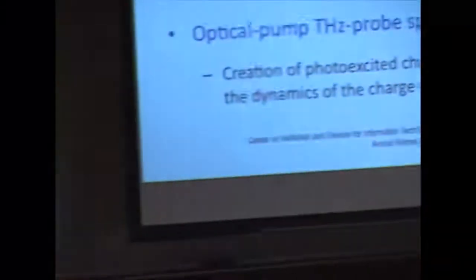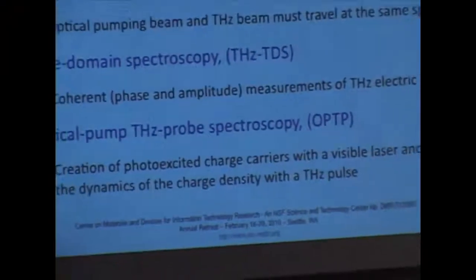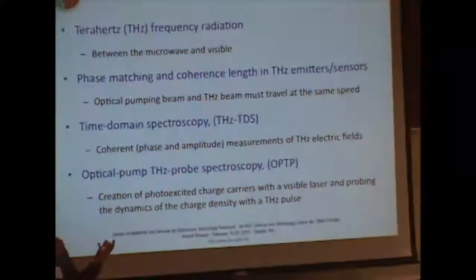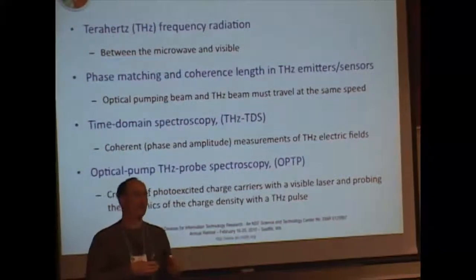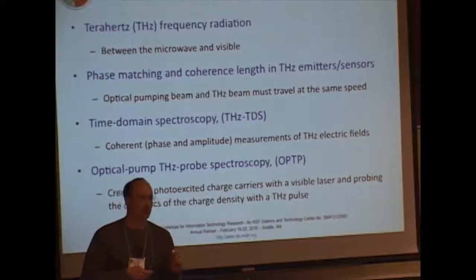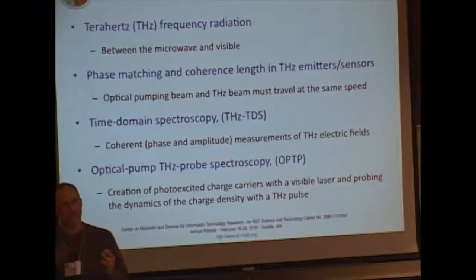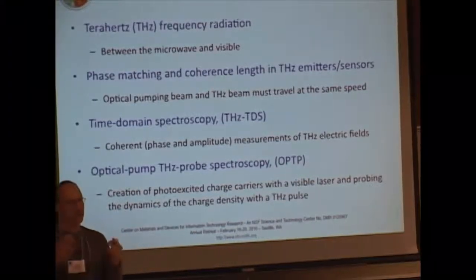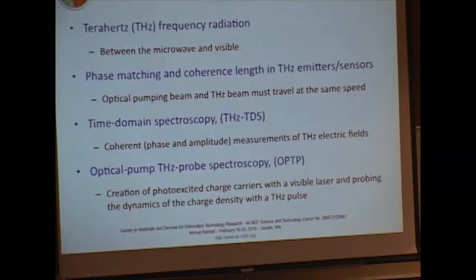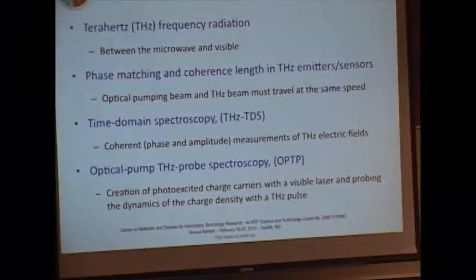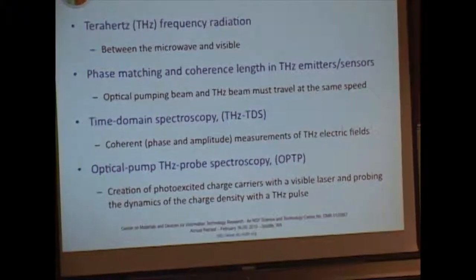And the last sort of vocabulary is optical pump terahertz probe spectroscopy. And this is what we're doing with organic photoconductors. Basically here we're creating some charge carriers by shining a visible light on the material. And once those charge carriers are created, we probe it with a very short terahertz pulse. Remember, the terahertz pulse is at frequencies that are very similar to the electron relaxation times and the recombination times in these materials. So it's very sensitive to the charge carriers.